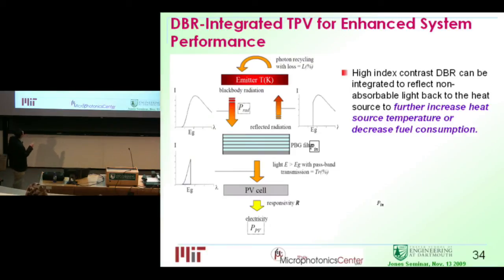So the device design is like this. Any semiconductor material will have a band gap. So for the wavelengths below the band gap, for the photon energy below the band gap, it's actually not going to absorb. So we're reflecting those photons back with a distributed Bragg reflector, as we talked about earlier. And then for the wavelengths we do absorb, we can get a filter to let it through, and then we convert that to electricity. And this reflected heat is not lost. It can further heat up the furnace temperature for a blue shifted spectrum so that you can generate more electricity from your cell, or you can decrease your fuel consumption while maintaining the same temperature.